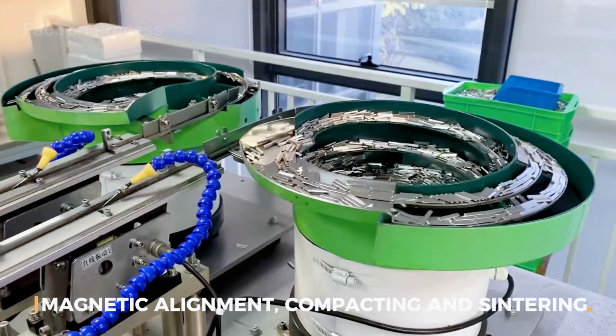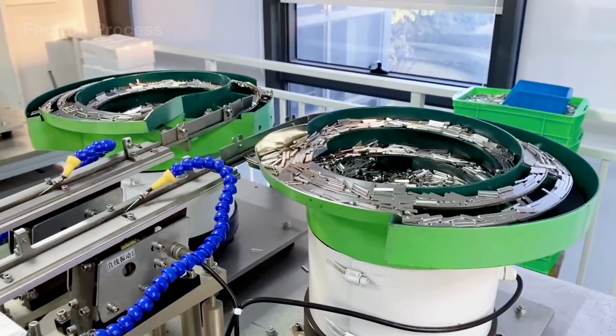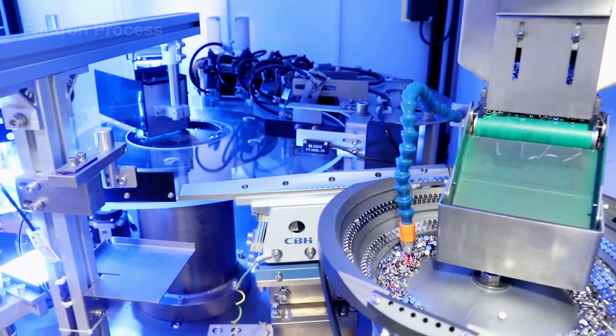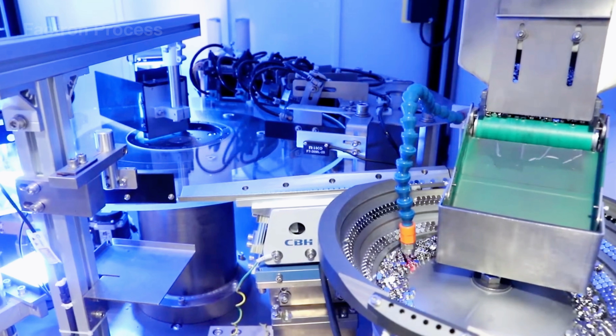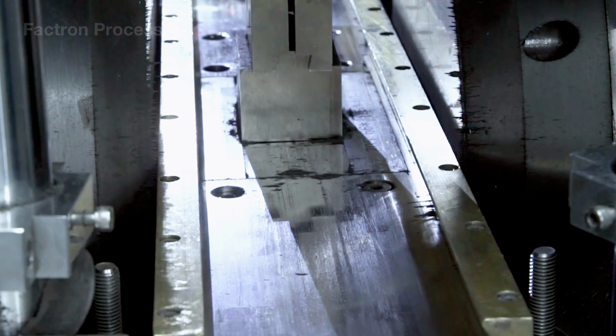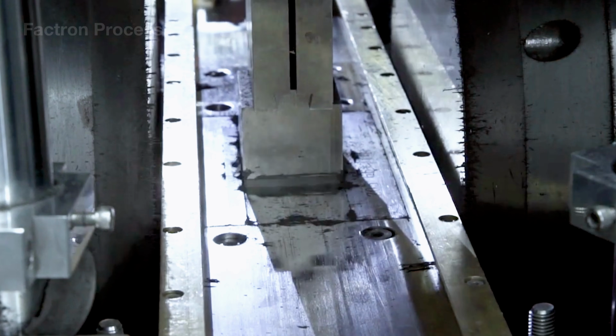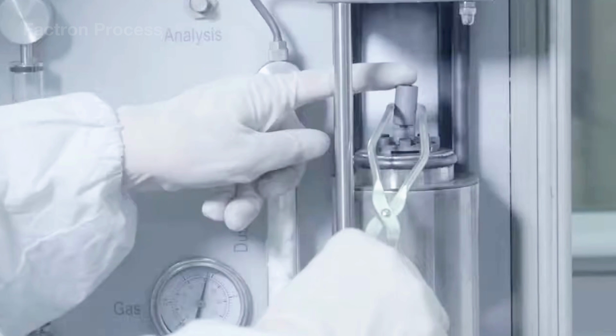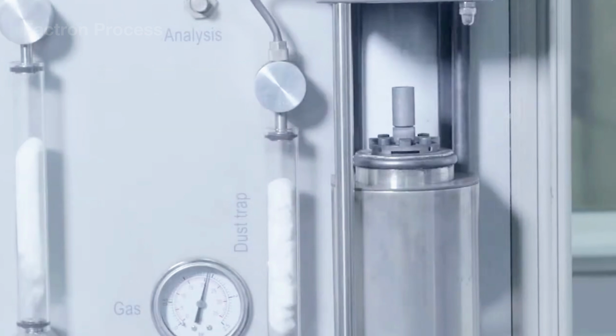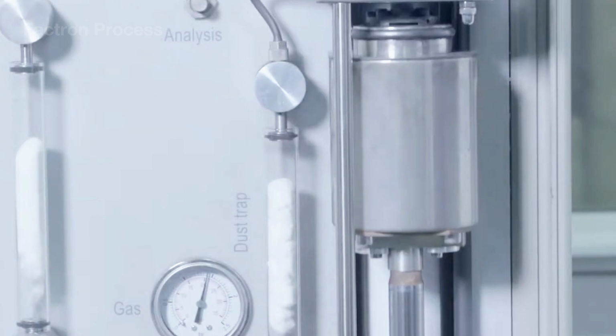The ultrafine NdFeB powder is loaded into a non-magnetic mold under controlled oxygen conditions. A magnetic field of 1.5 to 3.0 Tesla aligns the easy magnetization axes of the Nd2Fe14B particles before a hydraulic punch applies several tens of megapascals. The compact is then cold isostatically pressed at 200 to 300 MPa to improve density uniformity.